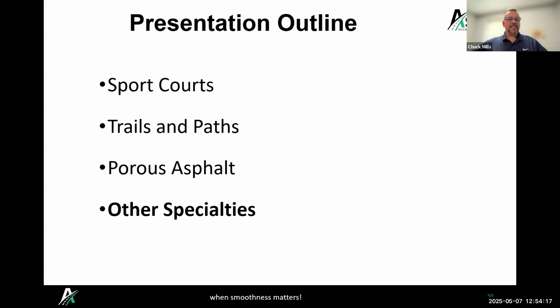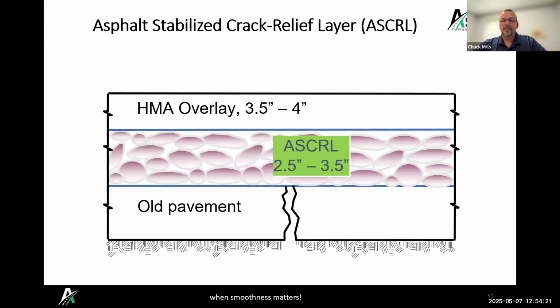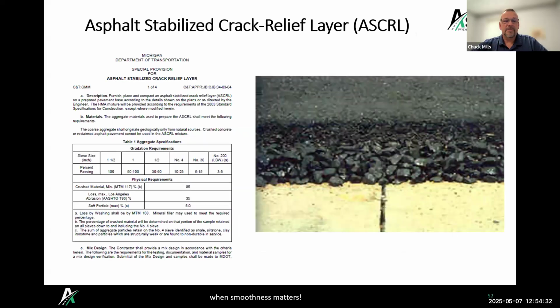Other kind of specialty mixes. I just wanted to touch on a few of them here. We have a mix that we call Asphalt. It's an asphalt stabilized crack relief layer. There is a specification for it. MDOT uses it over concrete pavements to reduce reflective cracking.